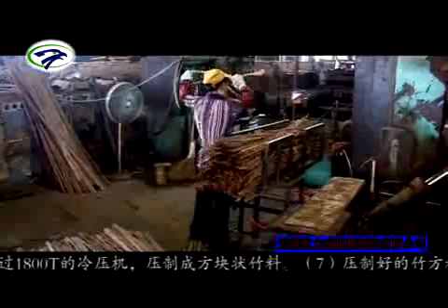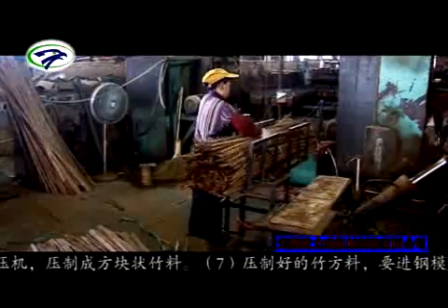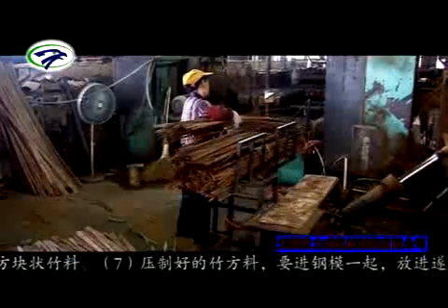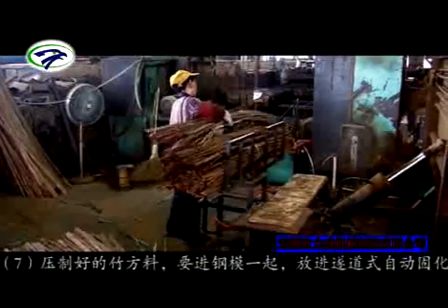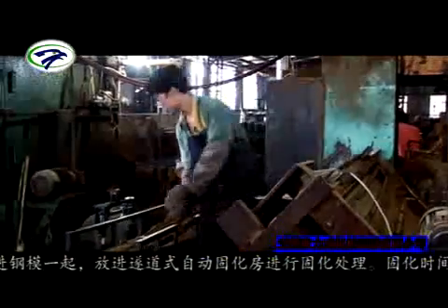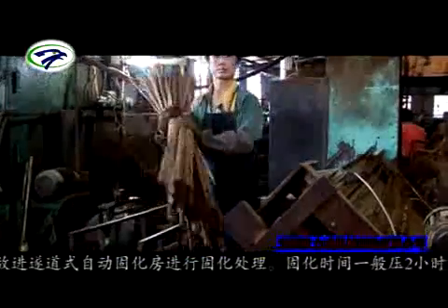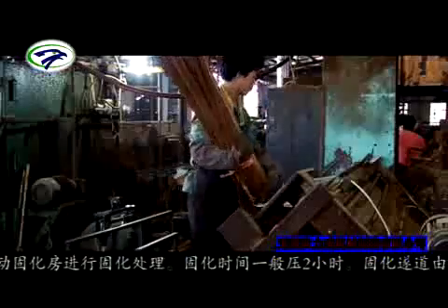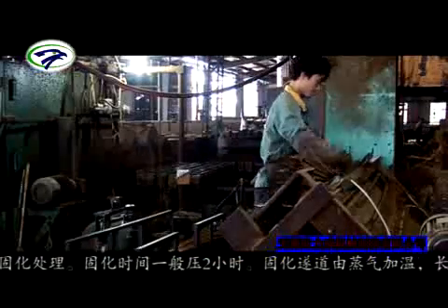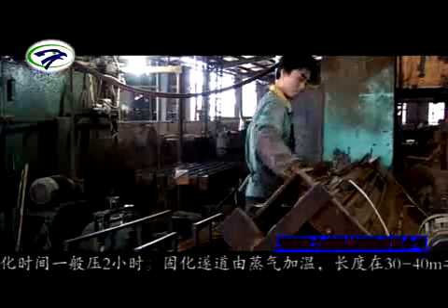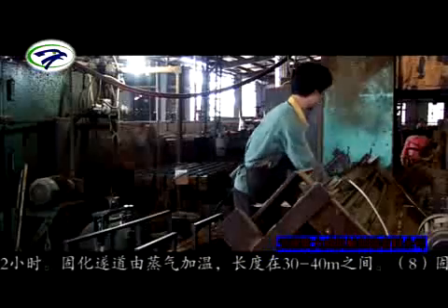7. The pressed material will be pulled into the tunnel-type automatic solidification room to carry on solidification processing for generally 2 hours along with the steel die. The curing tunnel is heated by steam and is between 30 to 40 meters in length.